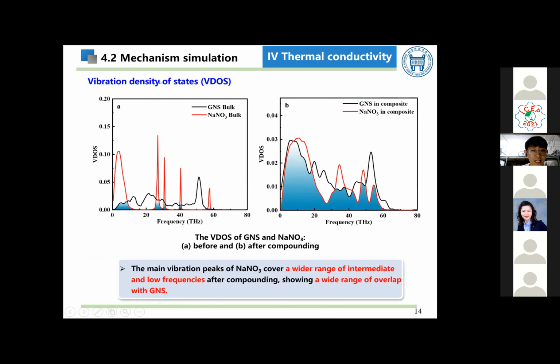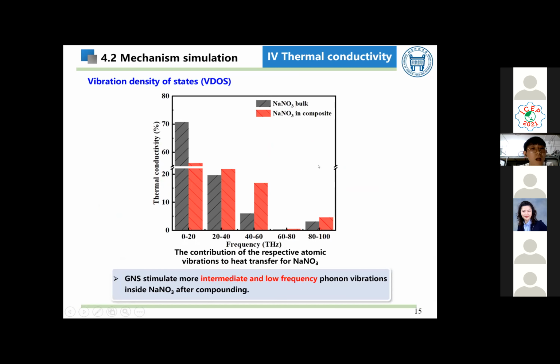the increase of thermal conductivity from a macroscopic perspective, the vibration density of the atoms before and after compounding was studied. It is obvious that the main vibration peaks of sodium nitrate cover a wider range of intermediate and low frequencies with GNS doped, showing a wide range of overlap with GNS. This means that phonon vibrations between the two match better, which indicates a higher thermal conductivity.